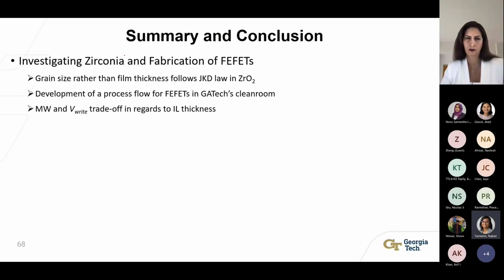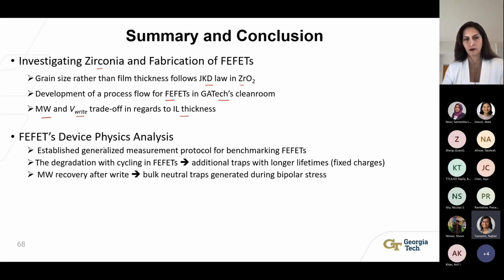So to summarize my entire thesis, my initial work on zirconium oxide showed that grain size rather than film thickness follows JKD law in zirconia films. Also, we were able to develop a process flow for FeFETs at Georgia Tech's clean room. And we also learned that there is an inherent trade-off between memory window and write voltage with respect to IL thickness. Then through my work on device physics analysis in FeFETs, we were able to establish a generalized measurement protocol for benchmarking FeFETs. We also learned that the degradation with cycling happens due to additional traps with longer lifetimes. Also, the MW recovery after write in FeFETs is possibly caused by bulk neutral traps generated during bipolar stress.